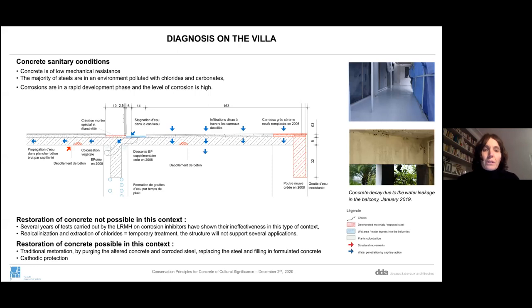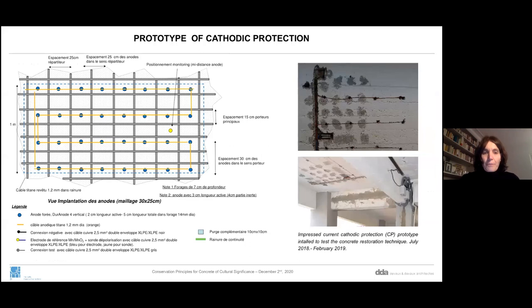In 2019, we installed a prototype for the cathodic protection with impressed current. And you see there the prototype. It's very invasive anyway, because you have the anodes every 30 centimeters and you have to connect all the steel. That means you make a lot of holes and a lot of trenches to put in the cables. And the idea was that you don't see anything after the intervention.